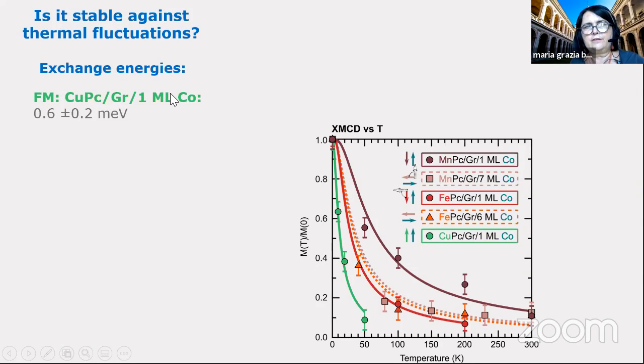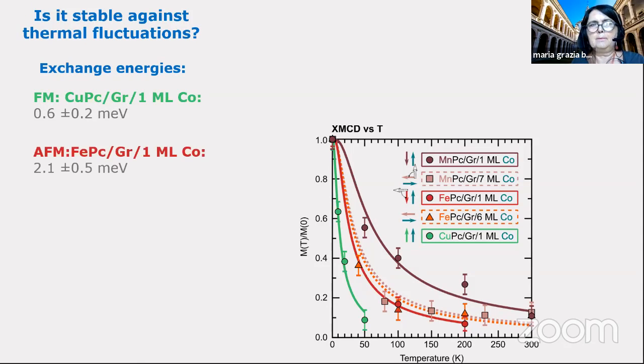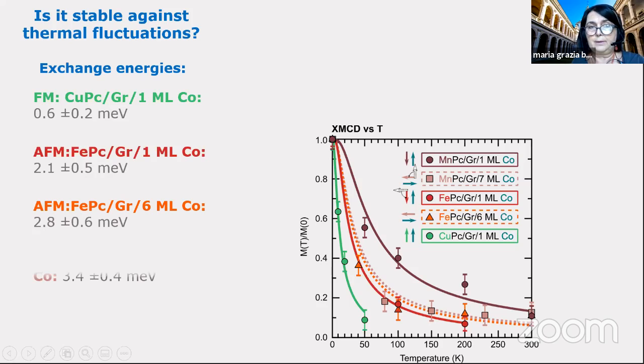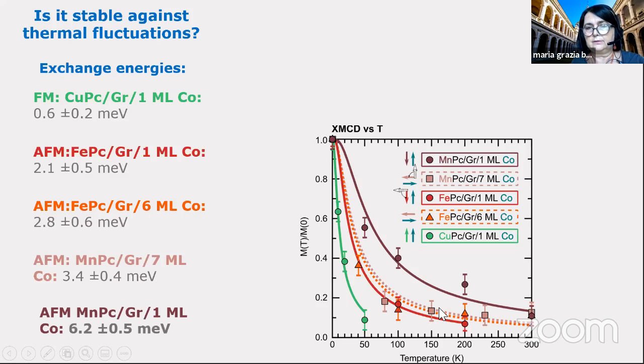You see, for the ferromagnetic coupling, the exchange energy is very low. In the system at 50 Kelvin, the magnetic state is completely destroyed. But for the antiferromagnetic coupling, for all these other systems, you will see that for the iron phthalocyanine, you have an exchange energy that is higher with respect to the ferromagnetic one, but lower with respect to the magnetic one, the manganese, sorry.